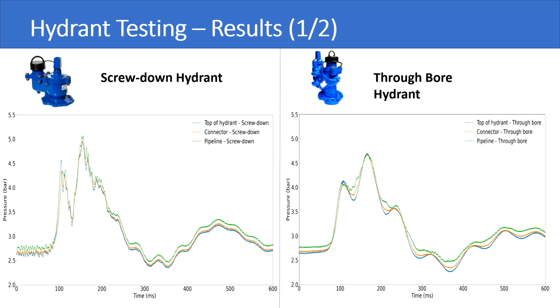We get different magnitudes. We get additional reflections for the screw-down hydrants, which is sort of expected because they're a more complicated shape. Yeah, they're vastly different, which would suggest that we cannot model them simply as we would a connector, and they would have an impact in the field on transient-based state localization methods.